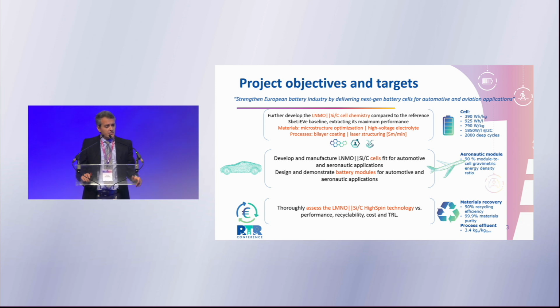The target gravimetric energy density that we have at cell level is 390 watt-hour per kilogram, for more than 900 watt-hour per liter in terms of volumetric energy density, and the cyclability of 2000 deep cycles from 90% down to 10% of discharge. The application of the technology is, of course, targeting as primary market the automotive market.